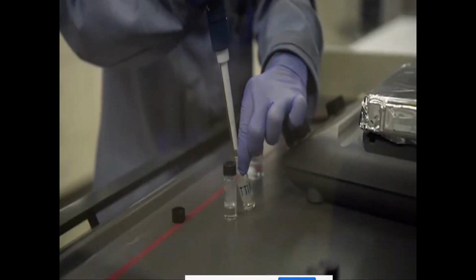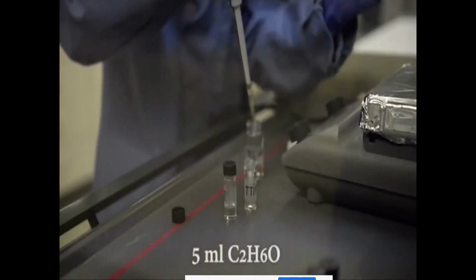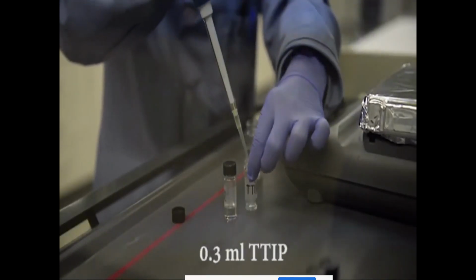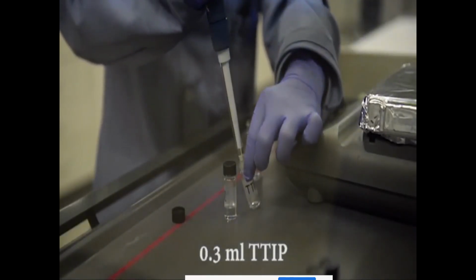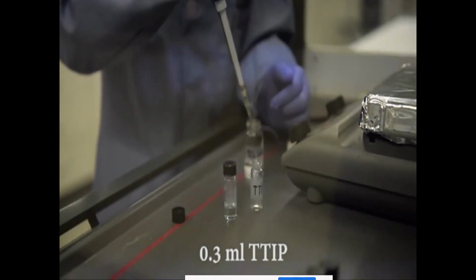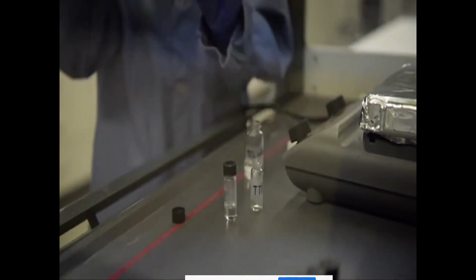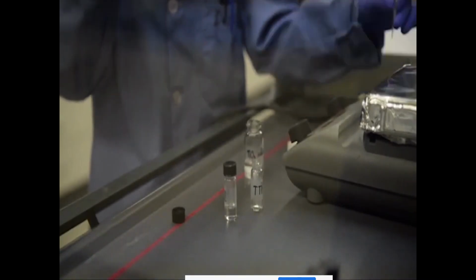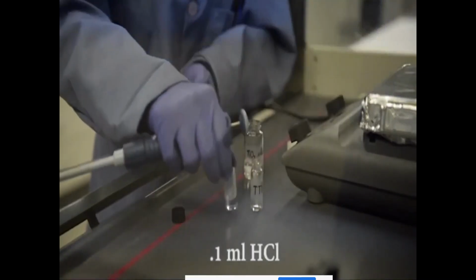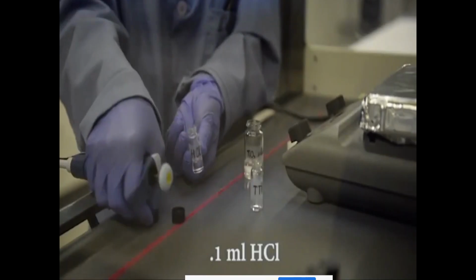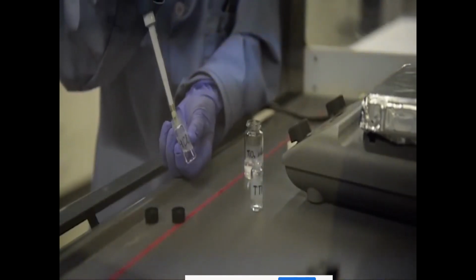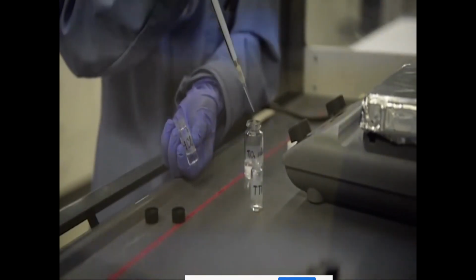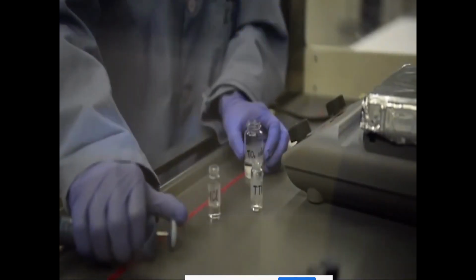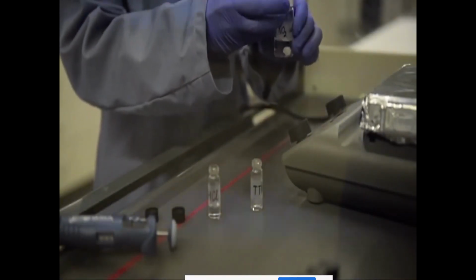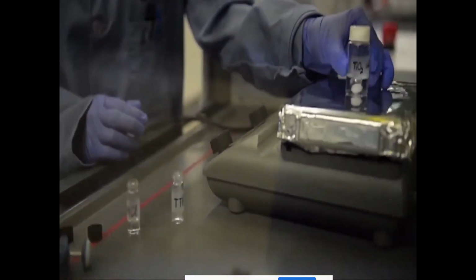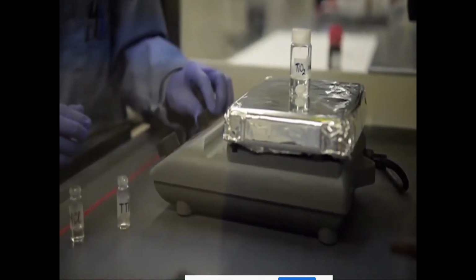To prepare the titanium solution, we use 5 ml of ethanol, 0.3 milliliter of titanium isopropoxide, and 0.1 milliliter of hydrochloric acid. After adding the three together, we let the solution stir at room temperature for about 10 minutes.